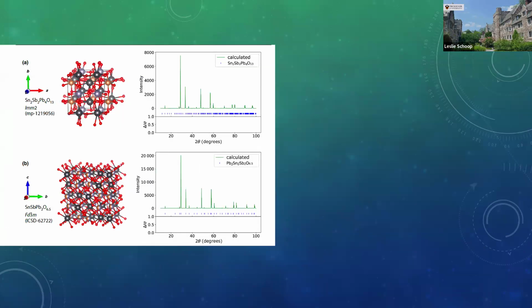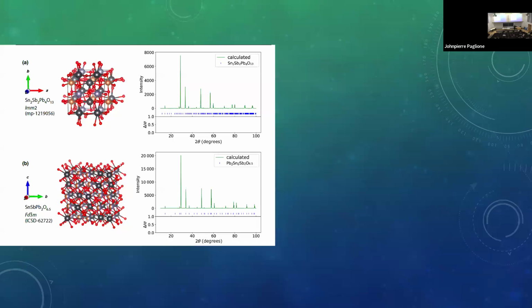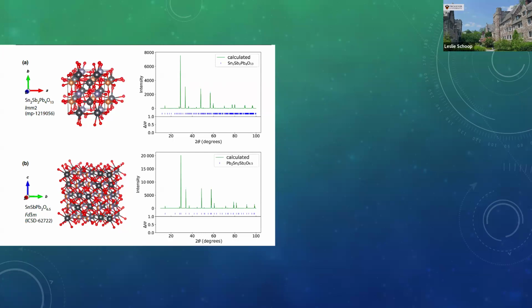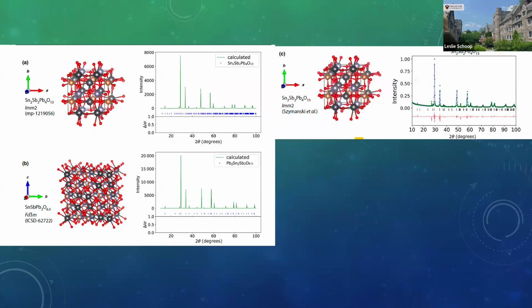And here, more of those examples, and you also see that powder X-ray diffraction isn't always an obvious indicator of this. So here, you see tin, antimony, lead, oxygen. Up here is the predicted new structure by Materials Project, and down here is a known structure, listed in the ICSD. One is orthorhombic, the other one is cubic. If I simulate the powder diffraction patterns, they look almost identical. So just with powder X-ray diffraction, I'm not going to see a difference between those two structures. How am I going to prove that I made the orthorhombic one and not the cubic one, right? If I just do powder X-ray diffraction, I need a lot more information for that.